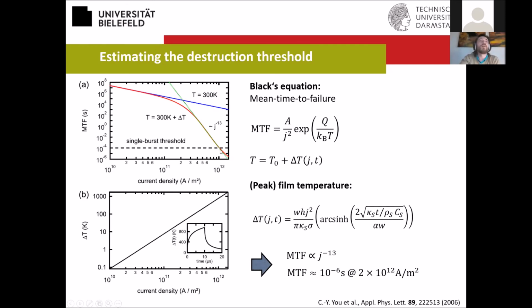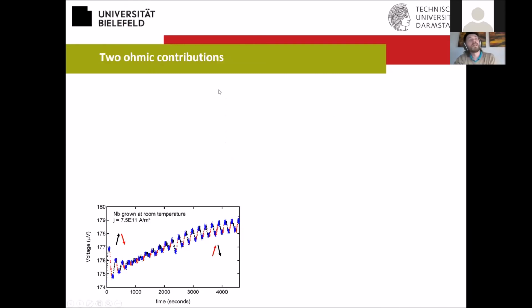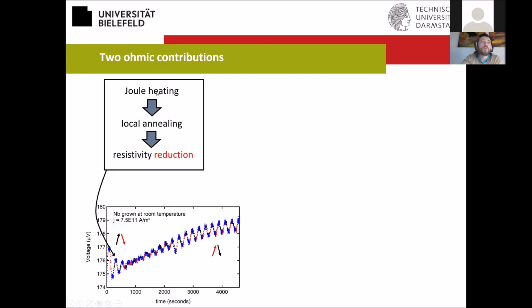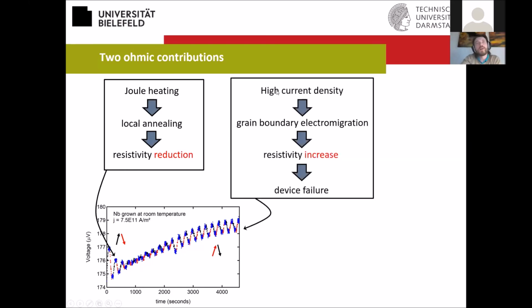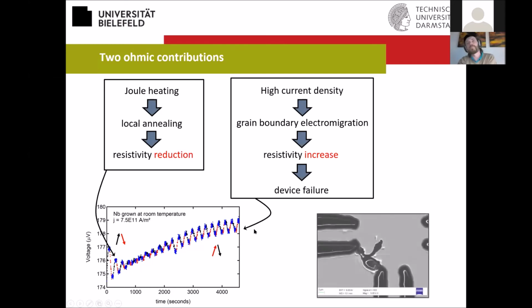Okay, so from this, it is pretty clear that eventually the destruction of our device is due to electromigration. In summary, this means we have 2 ohmic contributions. First, due to the Joule heating, we have a local annealing effect, and this leads to resistivity reduction. This is what we've seen here in this first part. And then, due to the high current density, we have some grain boundary electromigration. This leads to an increase of the resistivity because we destroy the grains, and eventually this leads to device failure. This leads to this opposite sign here, and finally to this breakdown of the devices.